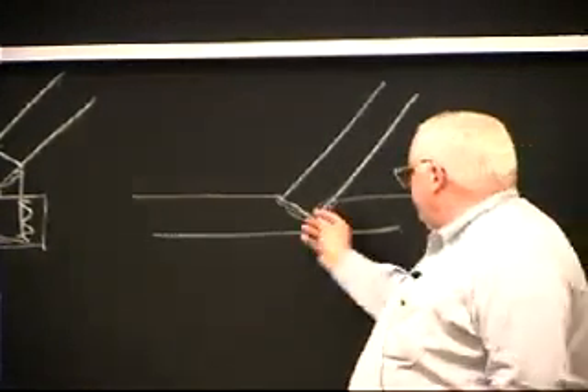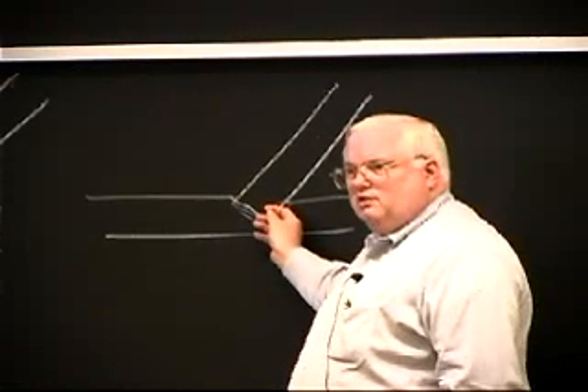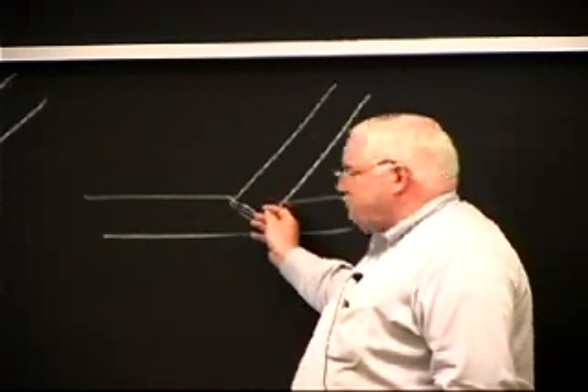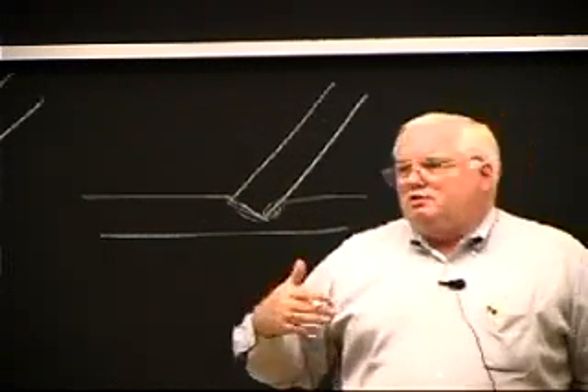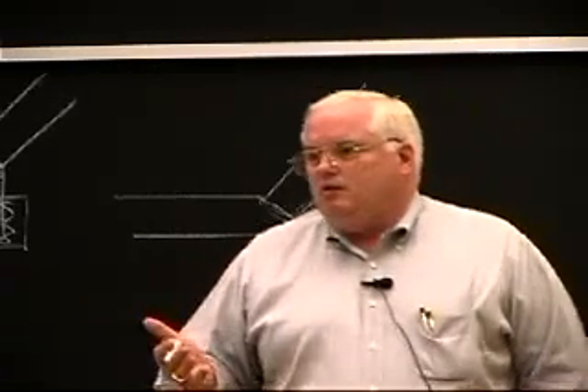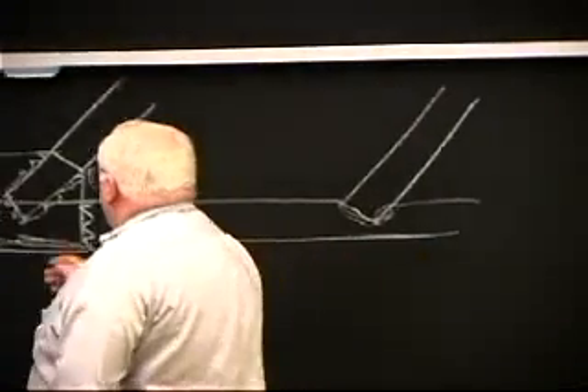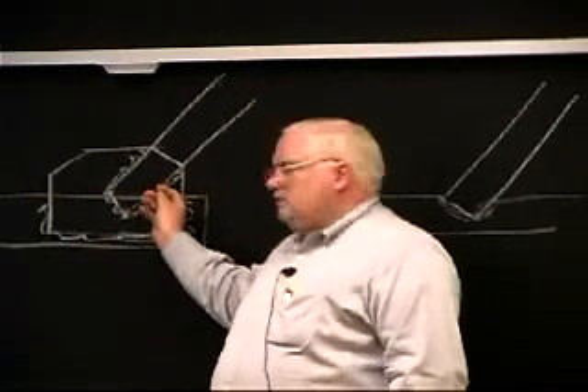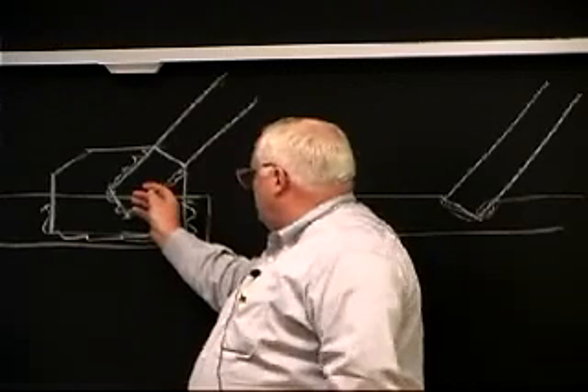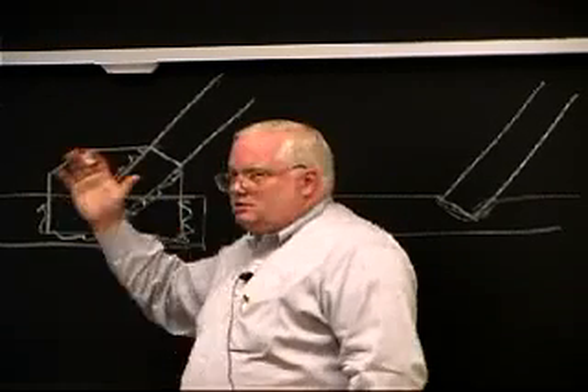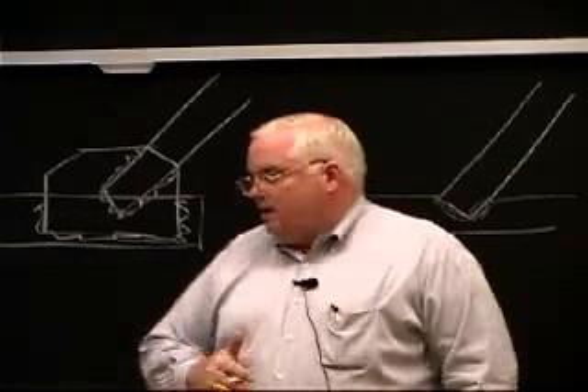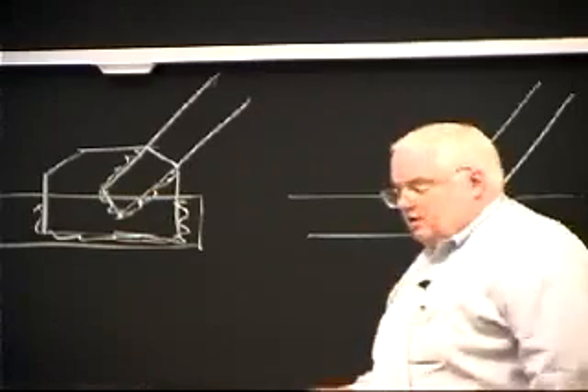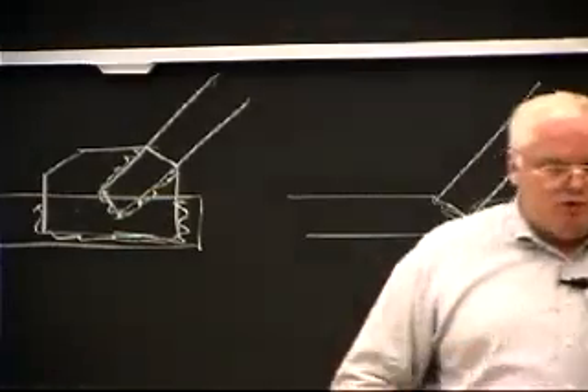The weld strength of the steel weld for typical strength steels is equal to, or maybe even 30–40% greater in the weld than in the base material, because the faster cooling rate of the steel gives a finer structure and greater strength. In the heat-treated aluminum alloys, I'm not going to have that advantage of a stronger weld, and so I do all kinds of things like put gussets and stuff in the structure, which just adds to the cost of the structure. But it is the typical way they do it.